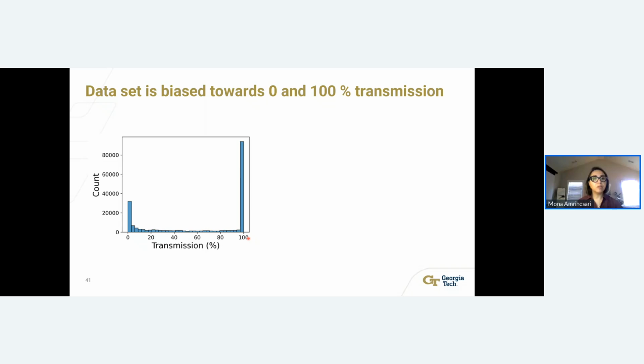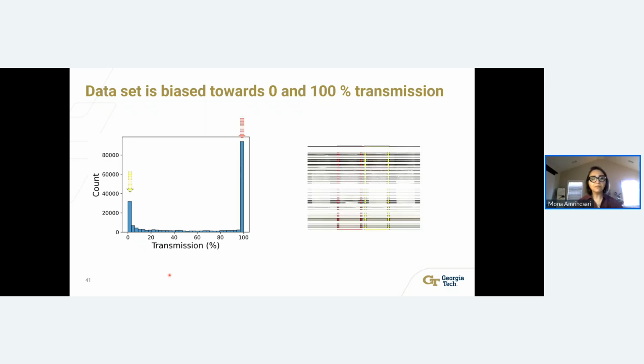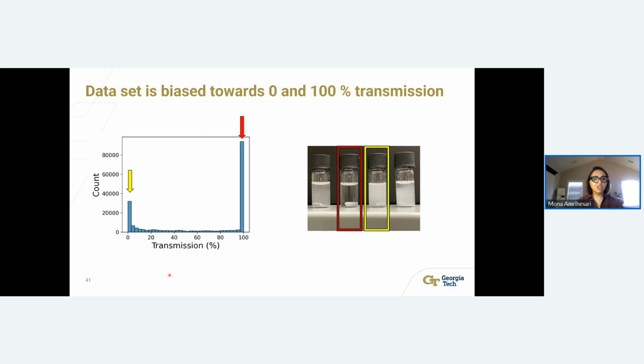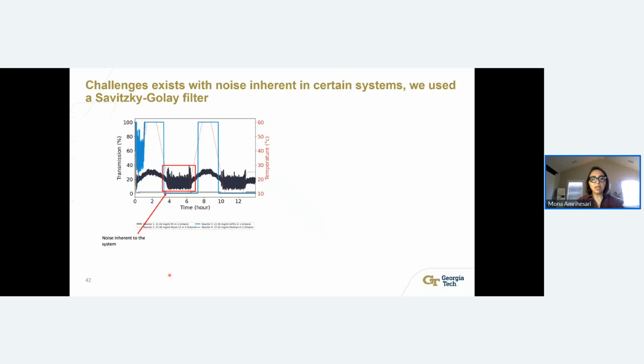We have 100% transmissivity, or biased towards the other end, which is 0%, meaning that either the polymer stayed soluble the whole time of the 2 cycles or stayed insoluble for the whole time. And we have a little bit of scarce data between this partial solubility region. So as these images also are corresponding to this 100% and 0%, there are other challenges also involved.